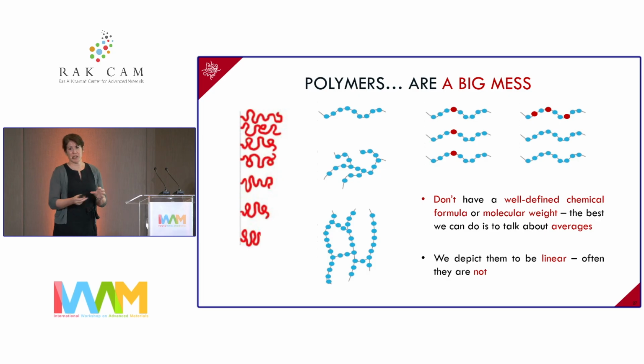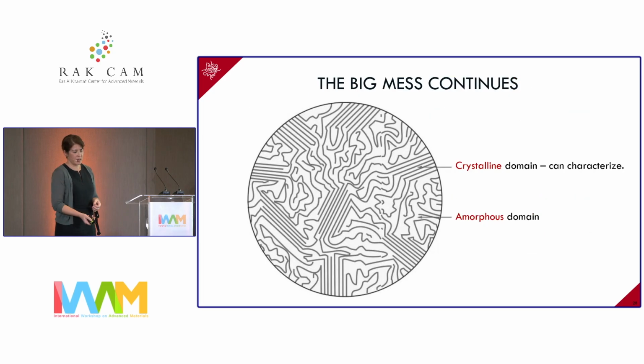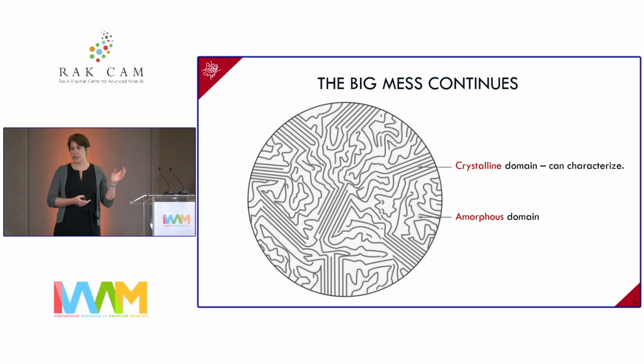And it's not just the chain structure that complicates things. If you now look at polymer morphology, quite often they're drawn to be semi-crystalline. So you have these crystalline domains and you have these amorphous domains. For the crystalline domain, we can use similar techniques that are used in inorganic crystalline materials to characterize. We can use X-ray, so we can use GIWAXS, and other techniques to look at those. But then the amorphous domain is very much blind to us. It's all about guesswork. And to be honest, for most polymer applications, this is fine.